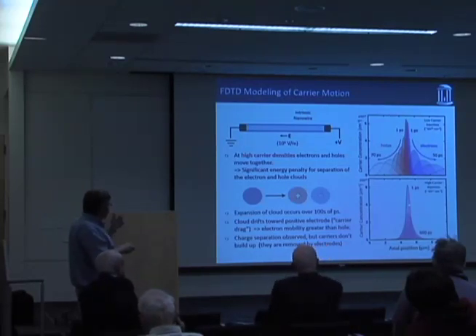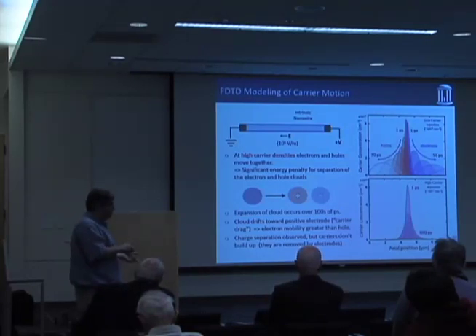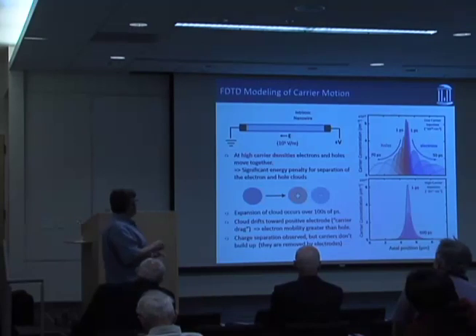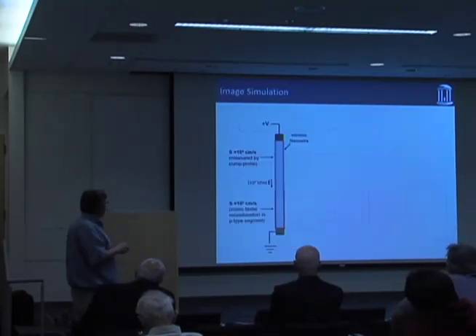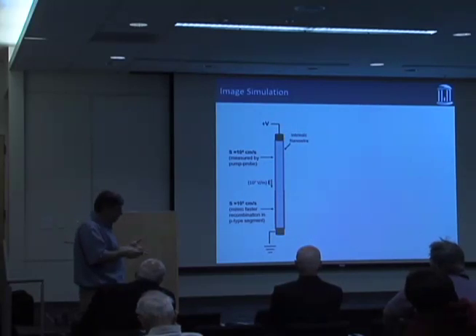And so the thing I want to point out here is, okay, this carrier density in the simulations is 2 orders of magnitude lower than what we have in the experiment. Okay, so we're way beyond this point in our experiment. And so we thought, okay, can we actually model our actual images?